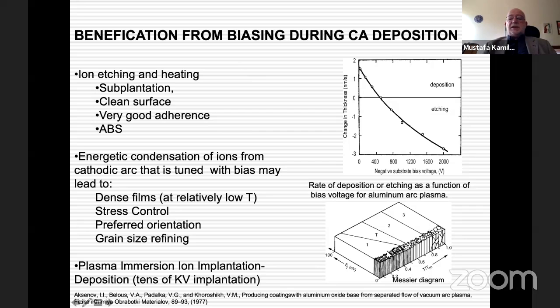So this is a Messier diagram that shows us how the structure of the coatings varies with the energy. The normal way of increasing the density and integrity of the coatings is increasing the substrate temperature. But we are limited in this increase of temperature because of the nature of the materials that we use. This is the melting point of the substrate material. So if you go to half of the melting point of the substrate, you get very dense structures.